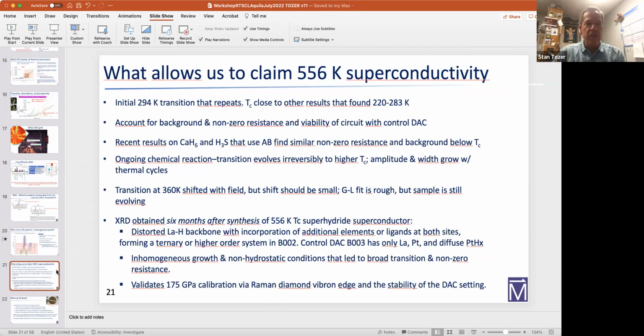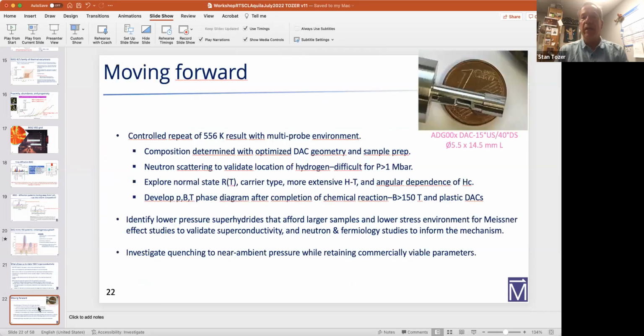So I've gone through all of this, what allows us to make the claim. X-ray verifies everything. Inhomogeneous growth validates the pressure and points to this distorted lanthanum hydride backbone. And then, we have to start out with this initial 294 Kelvin transition, and with thermal excursions move out to 556 Kelvin. So I'll put this slide up as, everybody knows what we need to do, and we need to reproduce. We're trying to do that now.